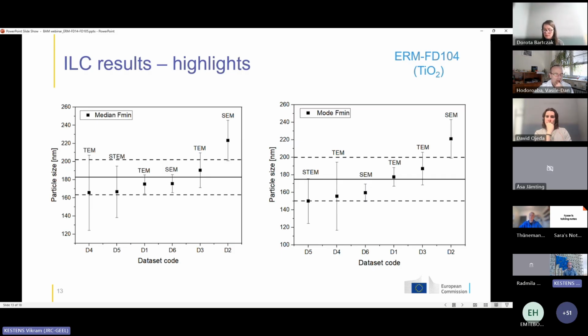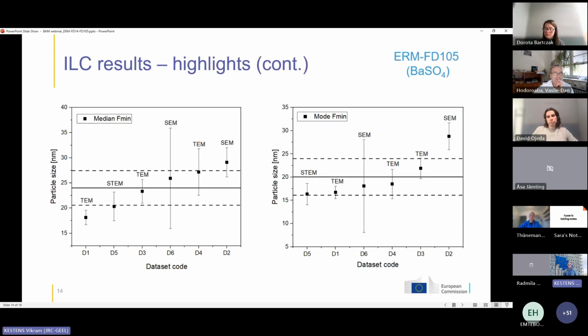So in the error bars, for some data sets, we have smaller uncertainties. For other data sets, we have some larger uncertainties. And this is linked to basically the reproducibility of the method that was employed by the laboratories. The same here. This is for ERM FD105, the barium sulfate reference material. Same observation. Most of the results agreed well, but for some laboratories we see small uncertainties. For other laboratories or data sets, we see quite large uncertainties.